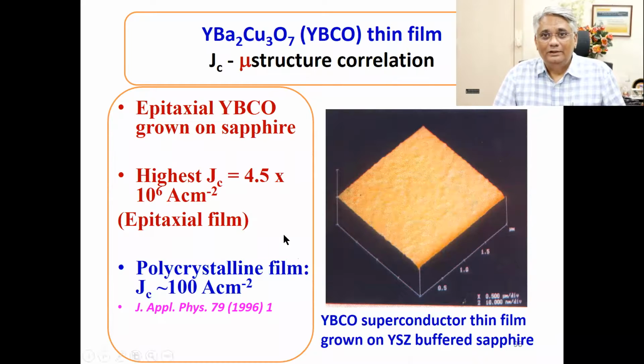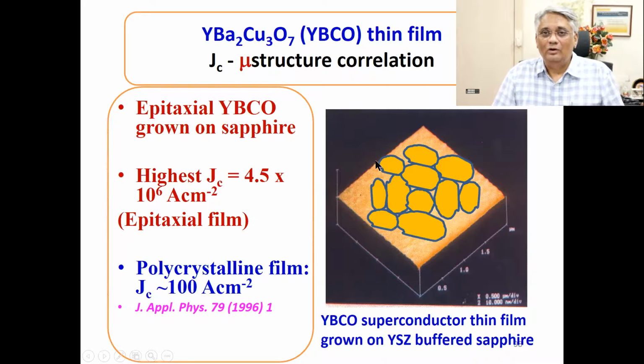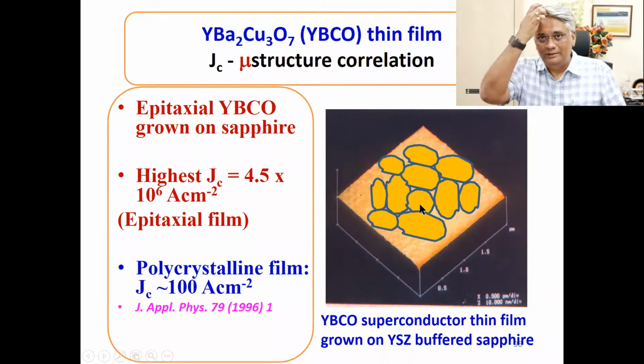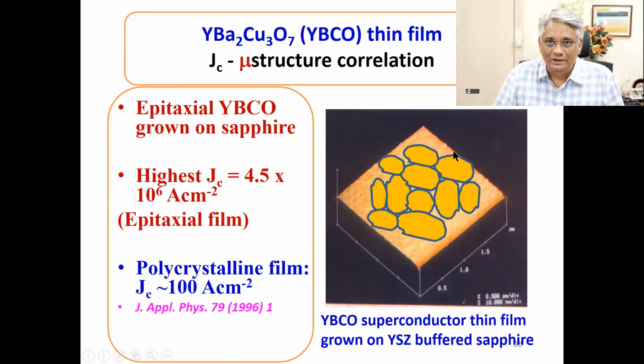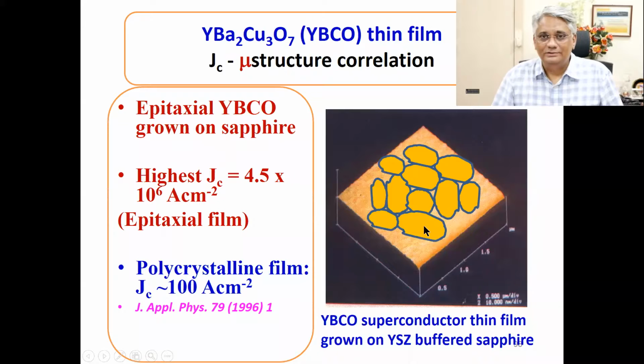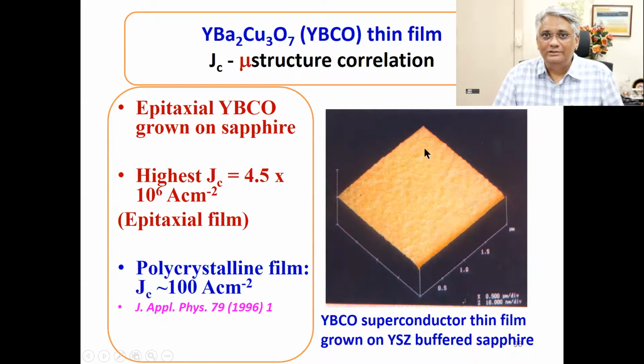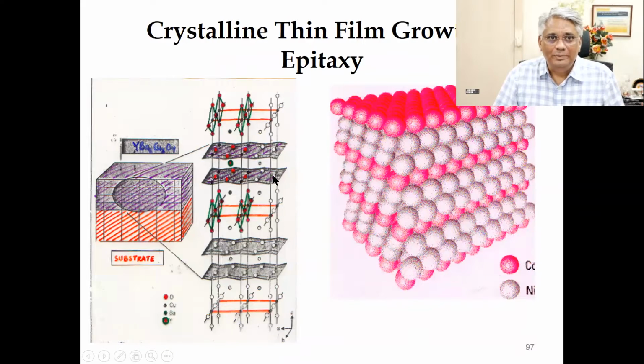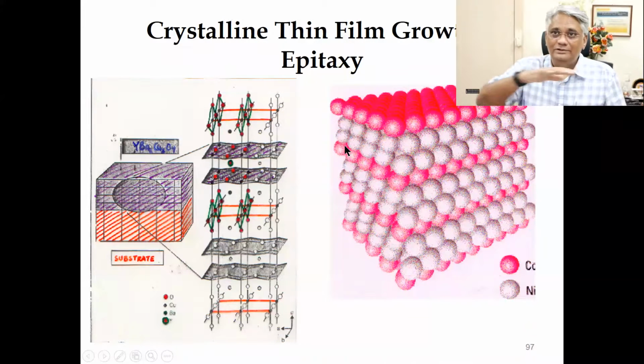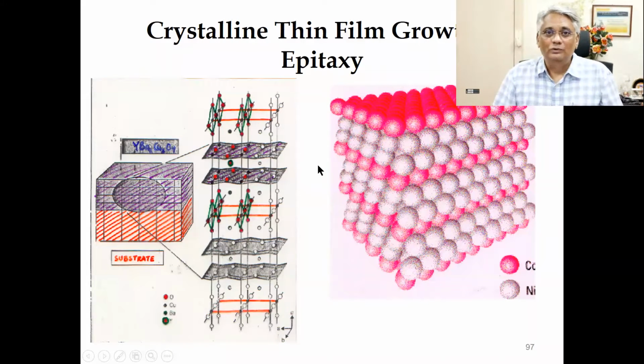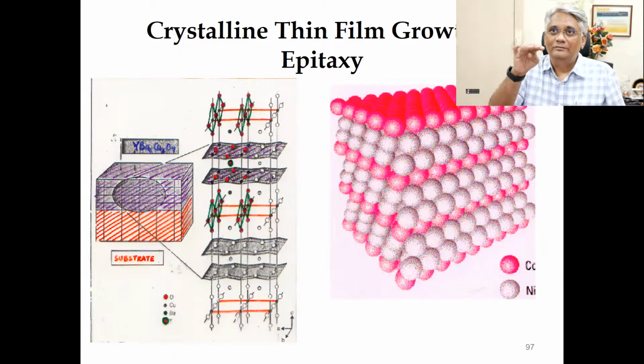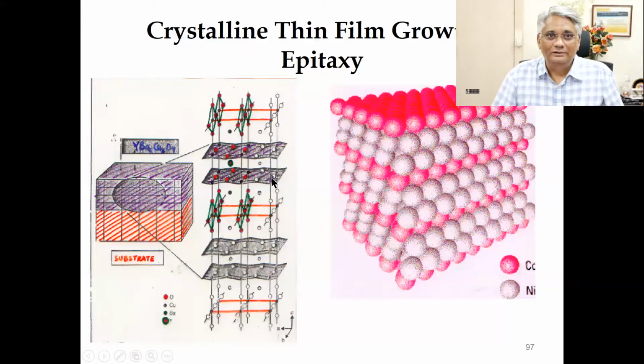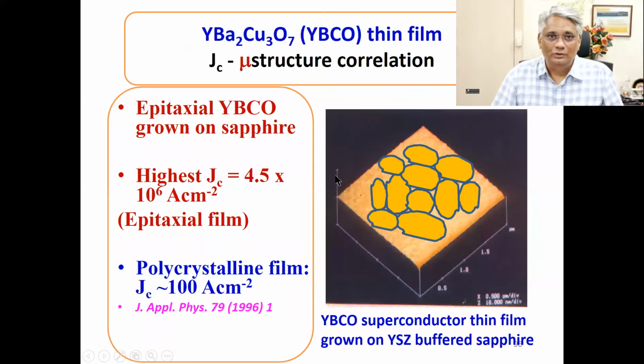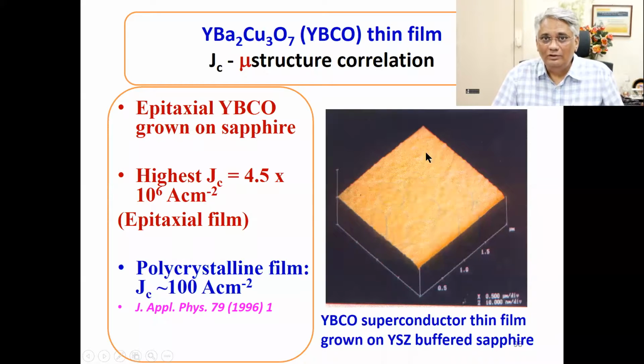Why? Let's say I got a thin film of yttrium barium copper oxide superconductor, and the thin film itself is polycrystalline in nature. That means a large number of grains and grain boundaries. Obviously, when the current is flowing, there is a large amount of grain boundary resistance. But when you grow a completely epitaxial thin film, it's a single grain. There is no hindrance to the flow of current, which means all these current carrying paths are uniformly arranged, and there is no misorientation. That means you have a small current carrying path. If the grain boundary is there, the current carrying path is lost, then it continues in the next region and so on. Right? That problem is there in this case, but not in that case.